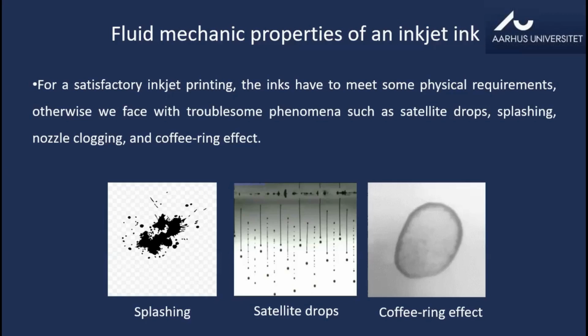Exactly. So it's basically the rate of evaporation of the material. Whenever you have any residue at the base of the cup, you leave the cup on the table, the material, because it's liquid, is going to start evaporating, right? And depending on the rate of evaporation, you would have segregation of the materials, because if the evaporation is too sudden, you would have the small particles being pushed to the side. It's basically a force that comes into play. And all the particles will segregate and agglomerate at the edges as against in the middle. And you have this kind of a ring effect being formed.